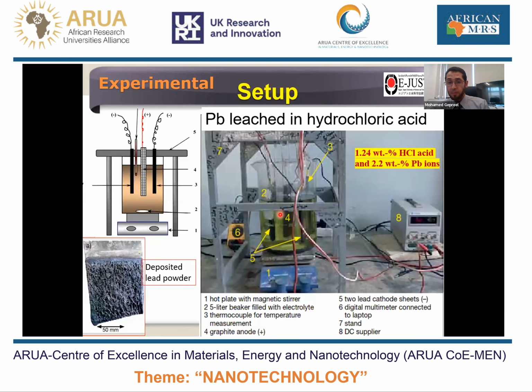This is the setup: this is the lead and lead oxide mixer, and these are the electrodes, the cathodes that deposit lead powder on them. Then we skim the lead powder after cleaning, then washing and drying. And drying and washing is actually one of the keys that gave us the idea today of making nanomaterial, nano lead and nano lead oxide.